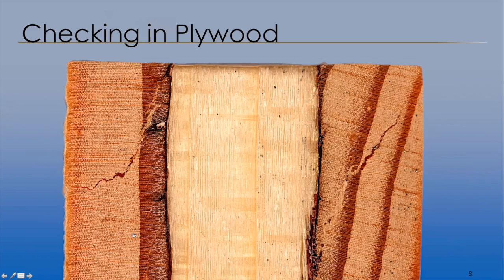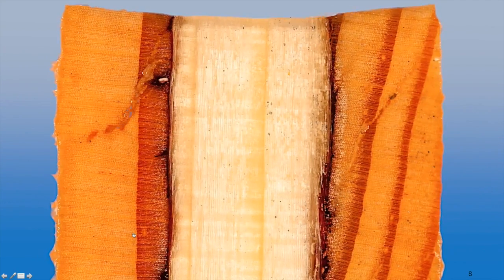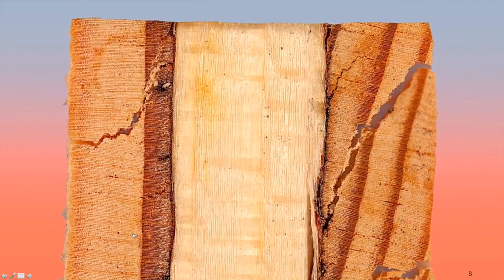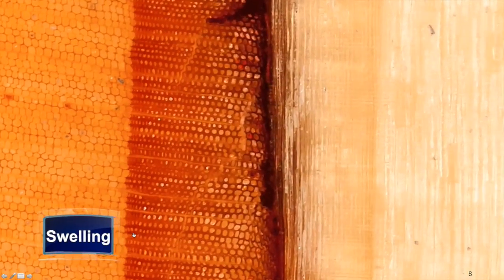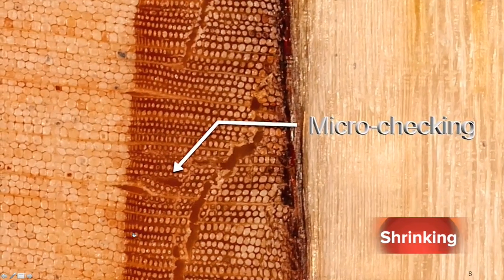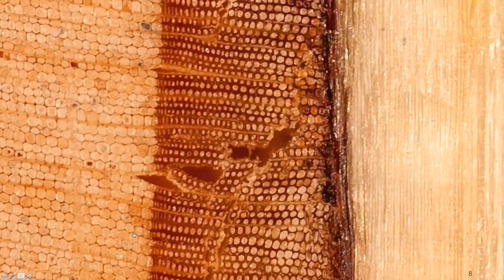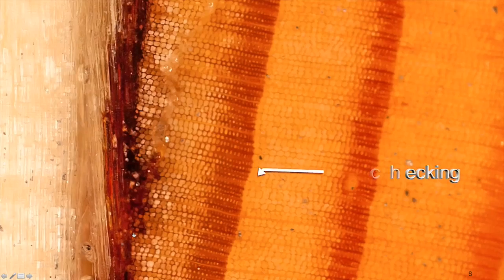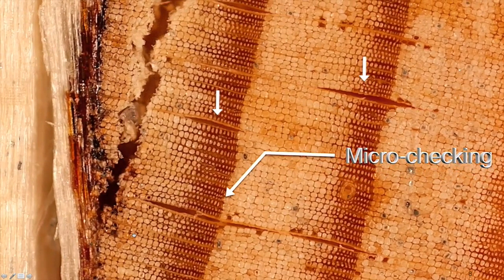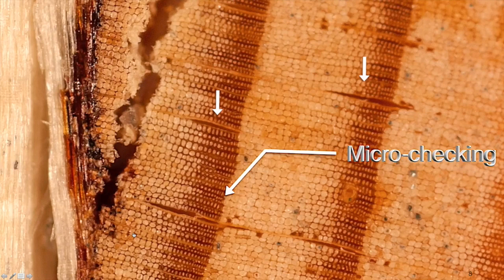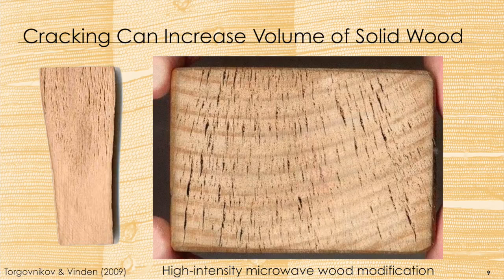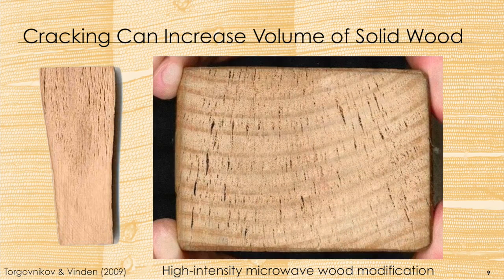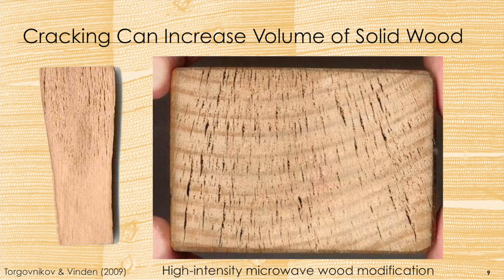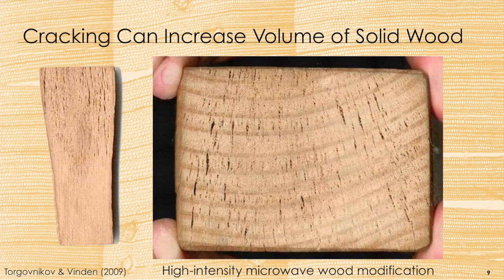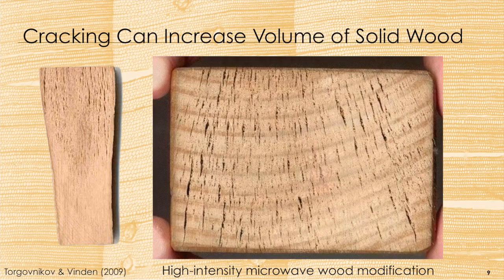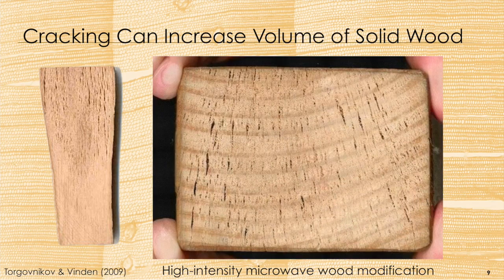And if you consider solid wood, there are some studies looking at checking or crack propagation. And like in solid wood, when we look at a composite such as plywood exposed to wetting and drying, we can see that it also develops microchecking. These microchecks are different from lathe checks that are introduced during peeling when plywood is manufactured. And if you consider solid wood again, there are some studies looking at how modification treatments using microwaves can increase the volume of wood, in this case by creating numerous internal microchecks due to high internal pressure.